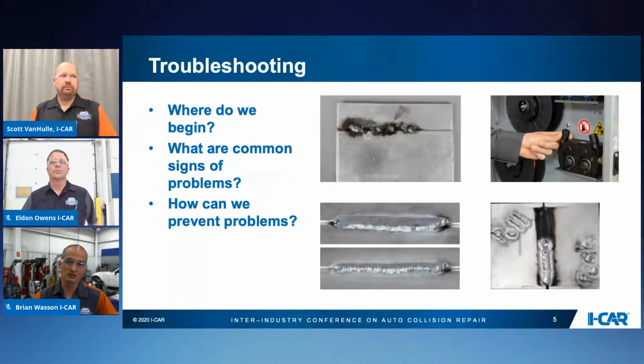If you're not going to be using it, I always say if it's going to be in the machine longer than a week and not being used, pull the spool out of the machine and put it in a Ziploc baggie, somewhere that isolates it from temperature and humidity. I usually put it in a Ziploc baggie and then put it inside the office or somewhere where it's cool and dry, and that will ensure that spool of wire stays fresh and doesn't form aluminum oxide on it. If you have a spool of wire with a lot of aluminum oxide formed on it because it's been in the machine too long, as you're welding you'll see black soot material in the weld puddle, and when you go to break the weld, it will have a lot of porosity in it.